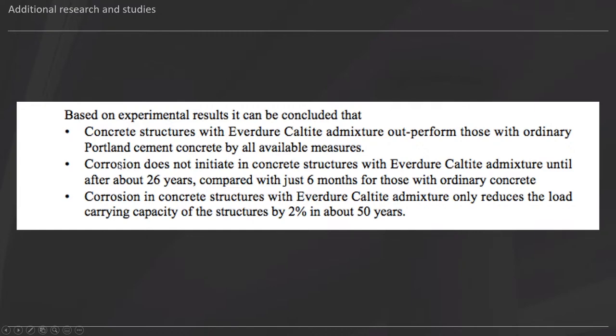And bear in mind, these are actual figures from the test, so this is accelerated test, and corrosion does not initiate in the structures with Everdure Caltite admixture until after about 26 years, compared with just 6 months for those with ordinary concrete. Then in the real world, we're not talking 26 years and 6 months, but you can judge from that, that's 52 times the life of the normal concrete. Corrosion in structures containing the Everdure Caltite admixture, it only reduces the load carrying capacity of the structures by about 2% in 50 years.